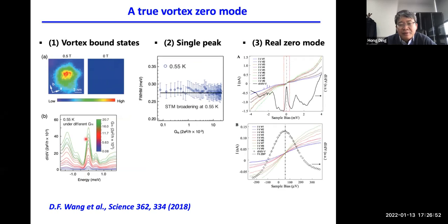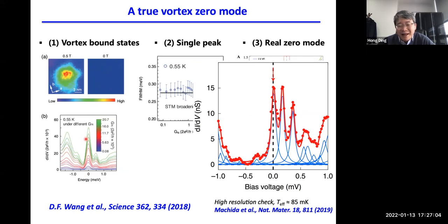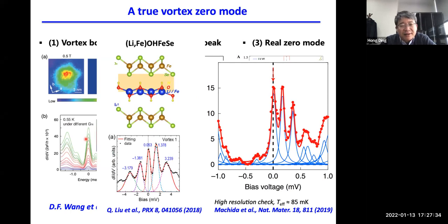And we really spent effort to calibrate the STM to make sure it's a real zero. And later on, as shown by a Japanese group, Hanaguri's group, using their super high resolution with an effective temperature of 85 millikelvin, they showed that this is actually a zero bias peak. And later on, the same thing has been found in other similar iron-based superconductors, lithium iron oxygen hydrogen, and iron selenium, doing the same thing.